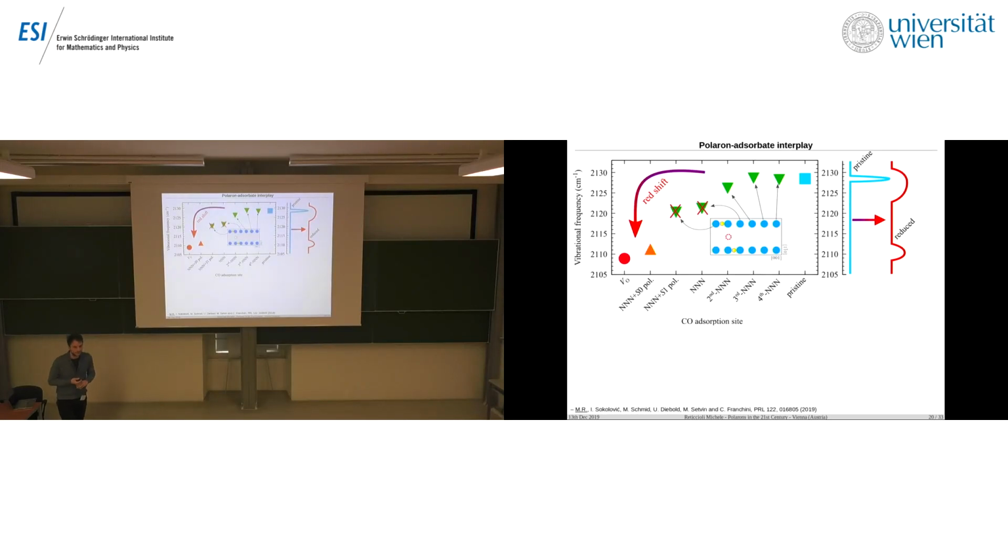If I may, I would like to add one more point. I cannot do the calculation in my head right now, but if you take our original interpretation, you have 4 shifted COs per oxygen vacancy, because you have these sites around it. Whereas in your picture, an oxygen defect generates 2 polarons, so you would have 2 per site. I think in our paper we did a quantitative analysis, but I have to check that. That may be a way to distinguish between the 2 cases, just comparing defect density, assuming that the polarons come from the defects. But I will have to check that.